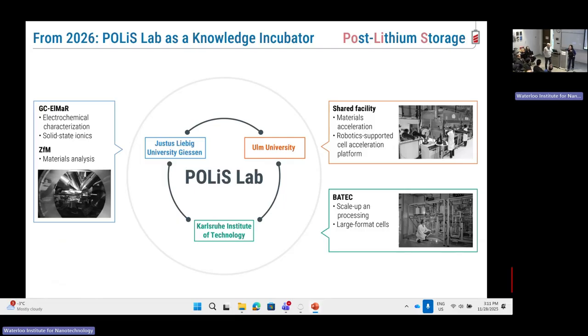Well, it's a good question. As I said at the beginning, thermodynamics can easily be calculated. So all the energetic properties of your cell can be well estimated, and we can estimate limits for that. Limits by thermodynamics. Kinetics have fewer natural limitations. If you ask what are limitations to kinetics by any natural law, I would say there are not so many. If you can lower activation barriers and so on, you can achieve very high rates.